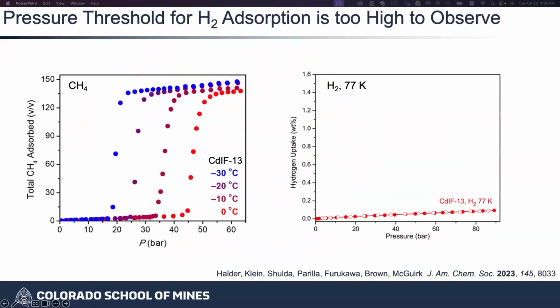But the reason why we're interested in this material and why we continue to study it is because it gives really beautiful step-shaped isotherms. So that type 5 or step-shaped isotherm I showed before, where in the original work we were looking at methane, and we can see that we don't have that type 1. What we have is a very flat pre-step region, and then there's some threshold, and then we see a step. And this was behaving really beautifully for methane, but when we went to study it for hydrogen, we could see that even at 77 K out to around 100 bar, we weren't seeing this response.